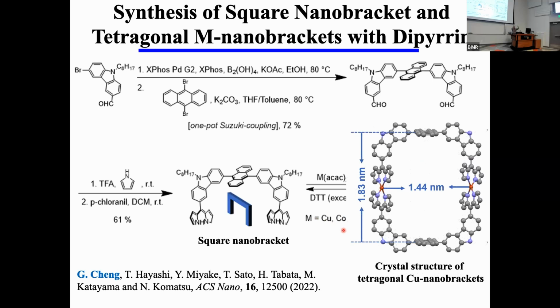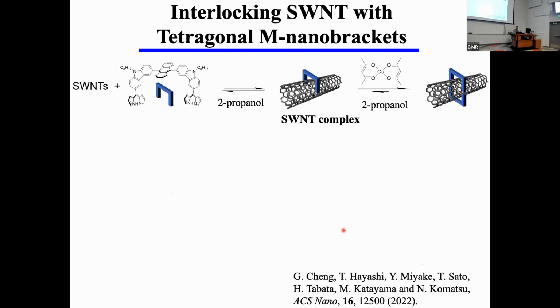So this is a kind of big nanocage. The width is 1.83 nanometer and 1.44 nanometer. It's a relatively very big cage. Of course, it has enough space to accept the carbon nanotube. And here is the strategy to interlock or to separate the carbon nanotube.